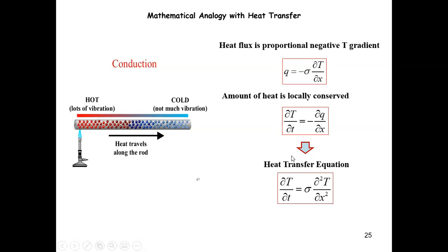So all of the solutions that we mentioned for solving the diffusion equation can immediately apply to the heat problem, and all of the homogenization of density fluctuation can also be applied to the homogenization of temperature fluctuations, and you also have this exponential decay for an initial high temperature region over long distance, etc. All of these hold, and we're going to use some of these results in our subsequent analysis when we talk about phase transformation, because we're going to worry about both the temperature profile in the material system and also the distribution of solutes.